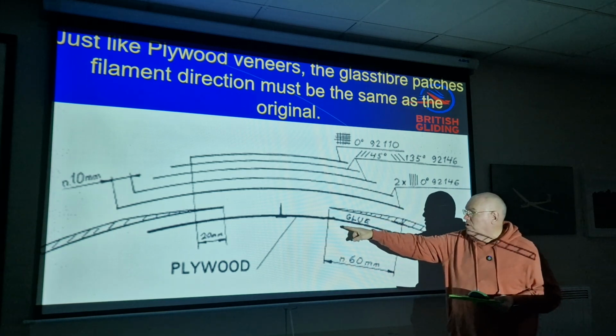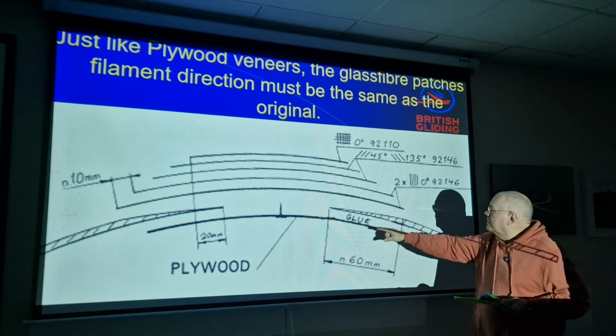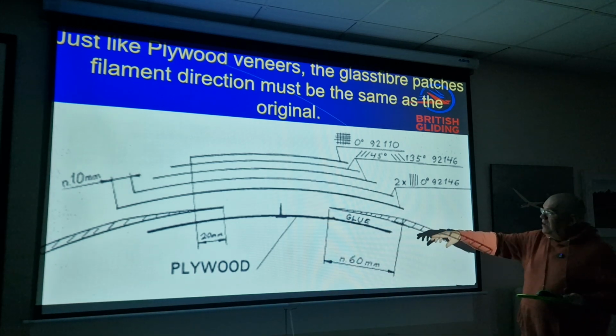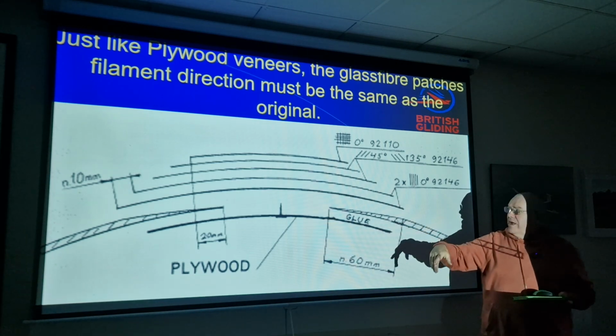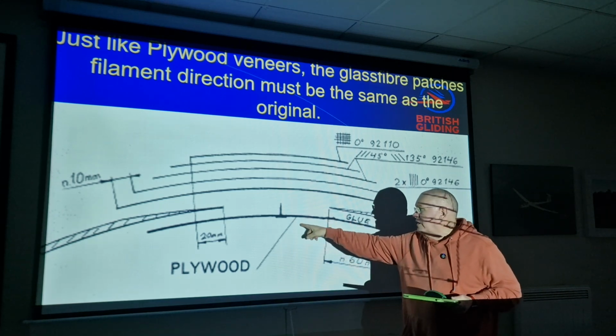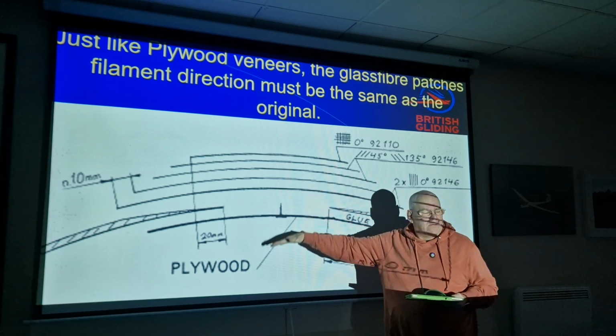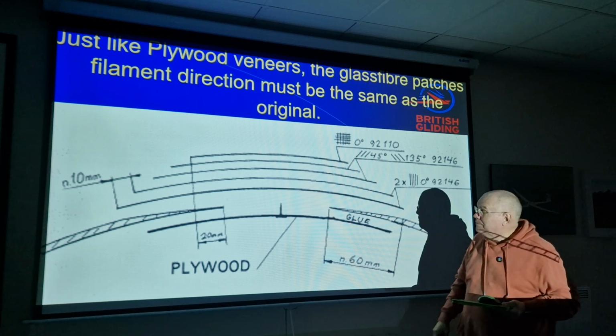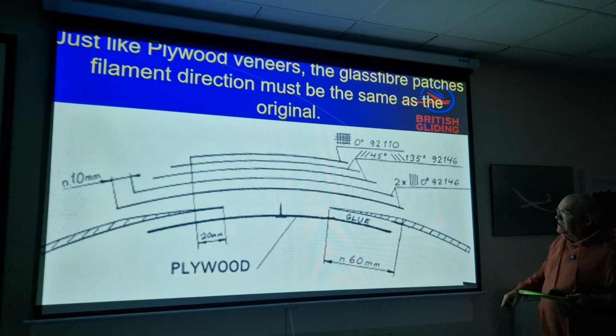They suggest you stick a bit of wood in there to act as a backer for the missing bit, which is quite normal, actually. If you can get to the wood after the repair, you put some cellophane or something on it, do the repair, then take the wood out. If you can't get to it, you leave the wood in, or you use another material like glass fibre.